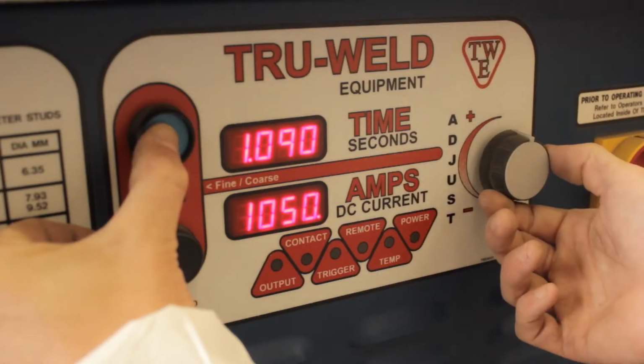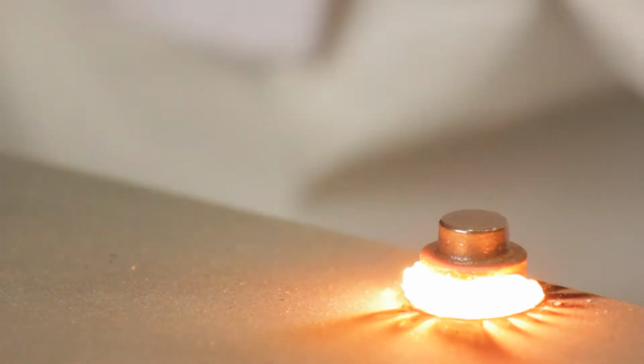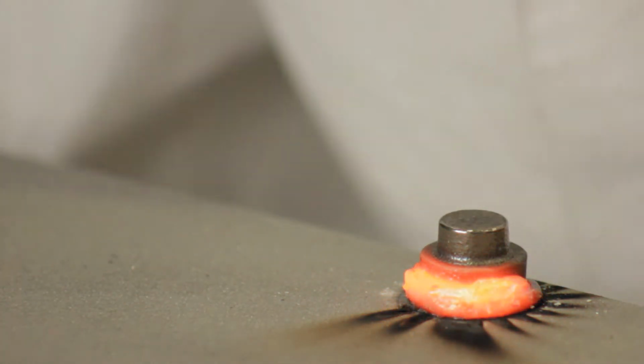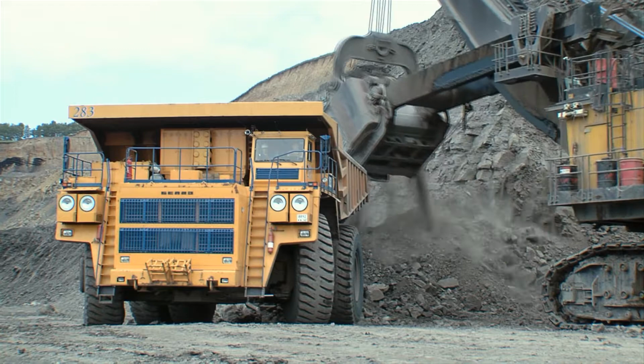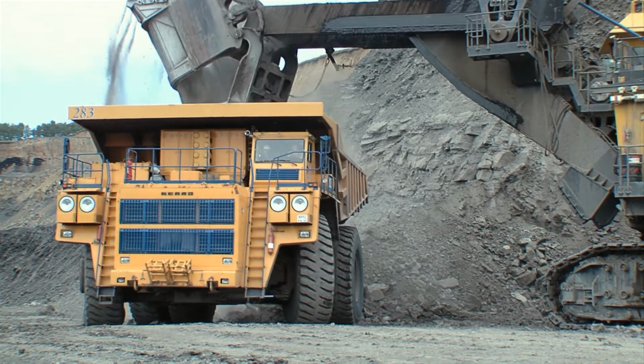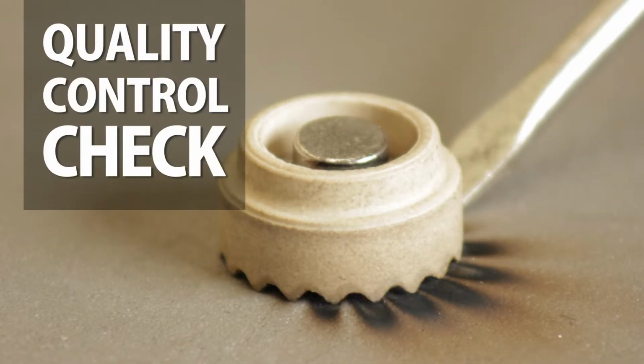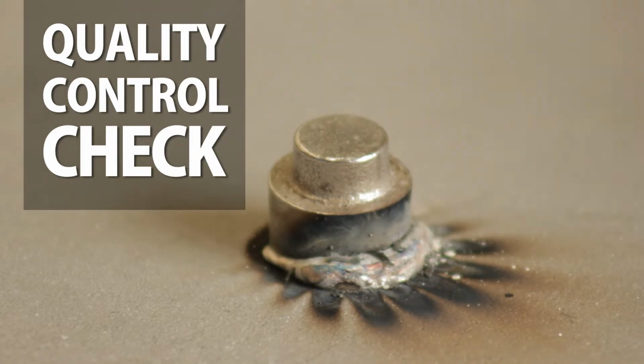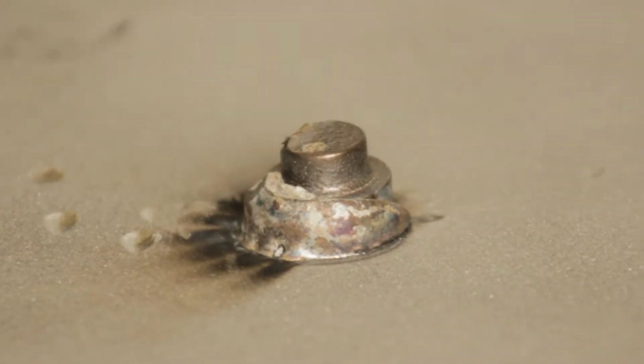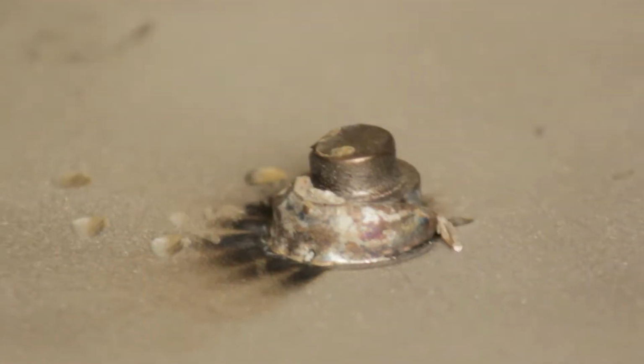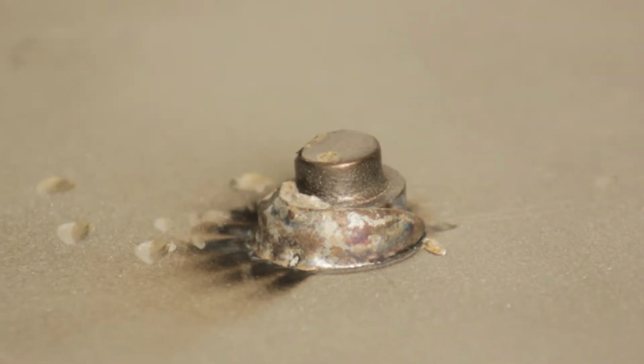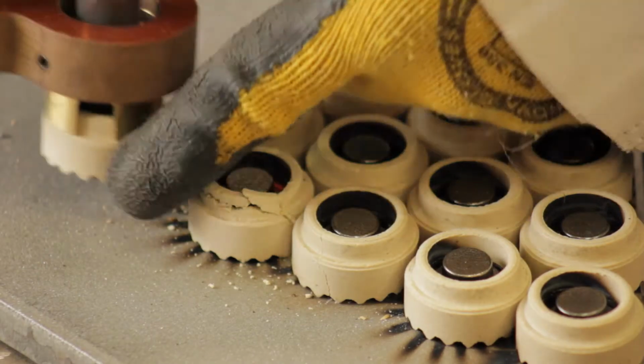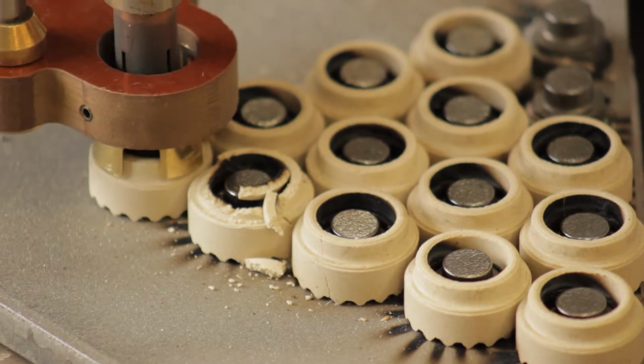Optimum time and power levels plus good plunge length will result in fully fused studs, studs more than able to withstand the heaviest of blows. Quality control check. Strike the welded stud 2 to 3 times with a 3-pound hammer. If the stud does not come out of the base material, the weld is good. You can then proceed to production welding.